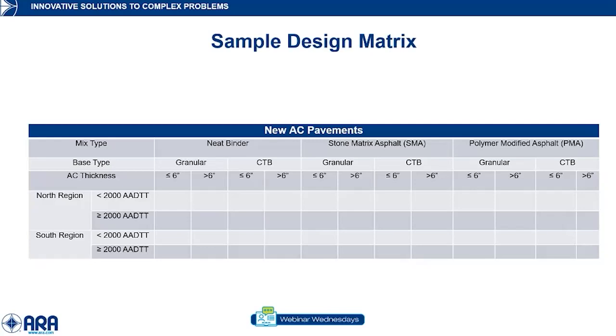new asphalt pavements. So we're in a state that has a number of neat binder mixes, and by neat binder, I mean there's no modification of the asphalt in the mixes. And then on their higher volume routes, they prefer to use stone matrix SMA mixes for the wearing surface. And then they also have a number of polymer modified asphalt sections as well. And you can take those and then further subdivide it by the type of prevalent bases that are used, which would be either unbound granular or cement treated bases.